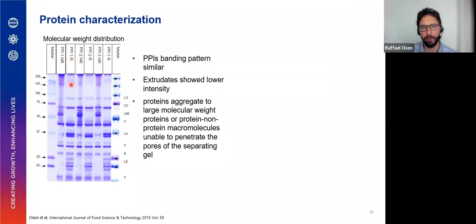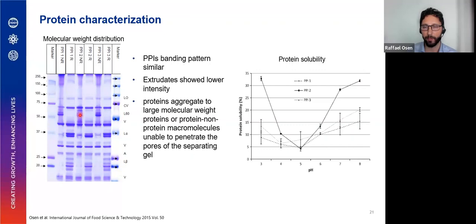In non-reducing as well as reducing conditions, we can see the legumin bands that are then dissociated into legumin alpha and legumin beta. Under non-reducing conditions, there's vicilin, there's convicilin. However, what we do see here is slightly more intense bands of legumin for protein number 2. So this could indicate a higher protein solubility. So we looked into that, and we did see that in the low and high pH range, protein number 2 did have a higher protein solubility compared to the other protein ingredients, which would explain partly this difference here in the molecular weight intensity.